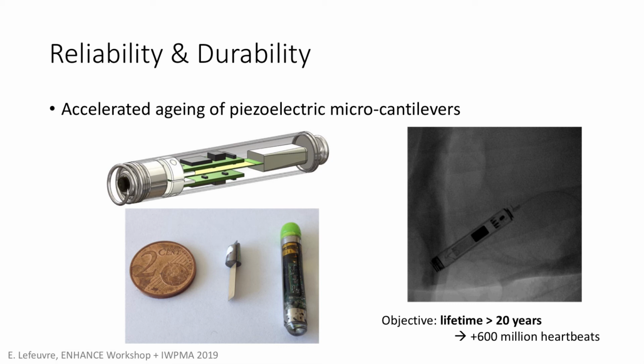So the cantilever itself was presented, but I show it again. It's here. It's composed of a very thin piezoelectric beam. It's a PZT bimorph made of bulk material thinned by mechanical grinding. And this is the tip mass, and this side is bonded on the capsule. So it oscillates. So you have here an artist view of the cantilever beam, the proof mass, and the capsule all around with the electronics and the screw to attach the pacemaker to the heart.